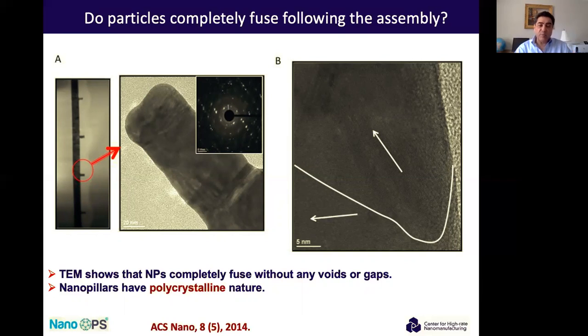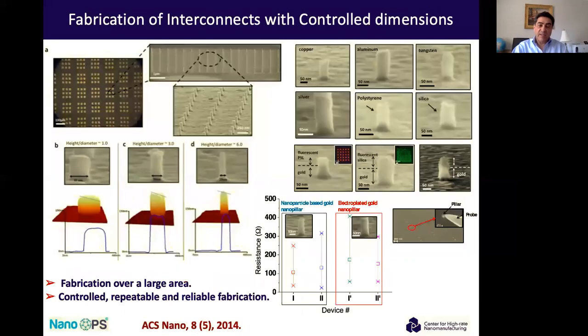There's no post-processing here. So the question is, okay, this looks good, but what about the conductivity? How does it compare to something that's deposited using another technique, such as electroplating or CVD? So we actually tried to look at a variety of things, and we got as small as 25 nanometers. This is 25 nanometers in diameter. And we've done copper, we've done aluminum, we've done tungsten, we've done silver, we've done gold, we've done even polymers and so forth.